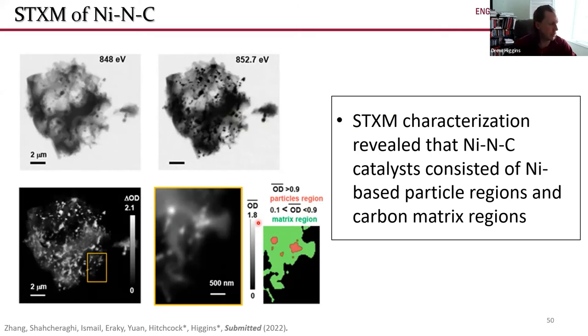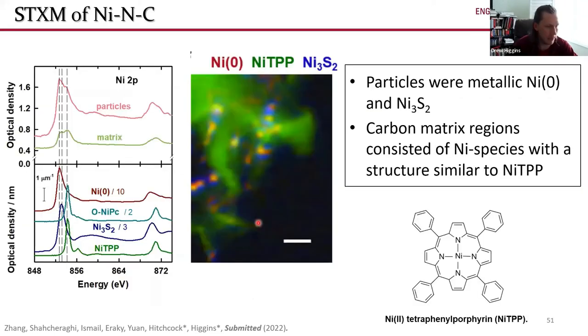So what we did is we separated the catalyst into those two distinct regions, the particles and the carbonaceous matrix, and we integrated the spectra that we collected from that. And so the results of those spectra are shown on the left here. This kind of pinkish red color is the spectra that's collected for the particles. And this green is the spectra that was collected for this carbonaceous matrix.